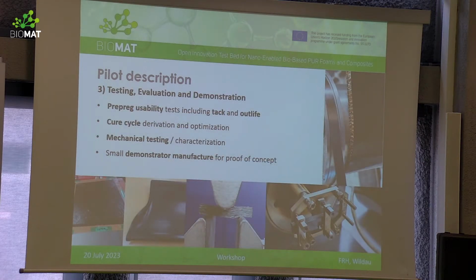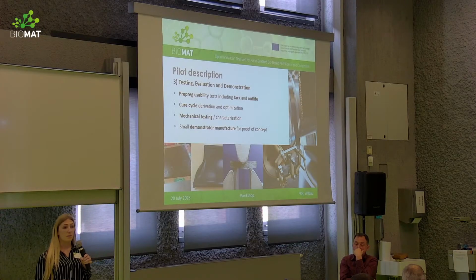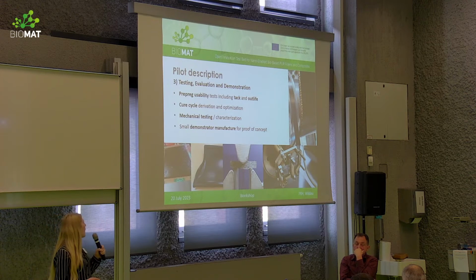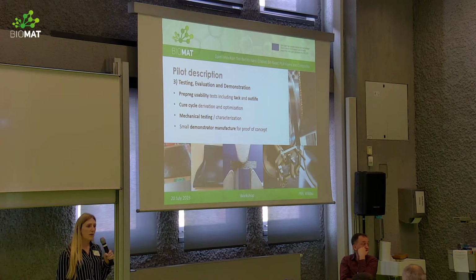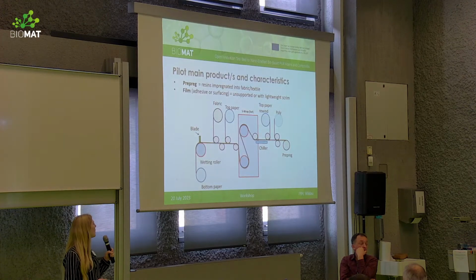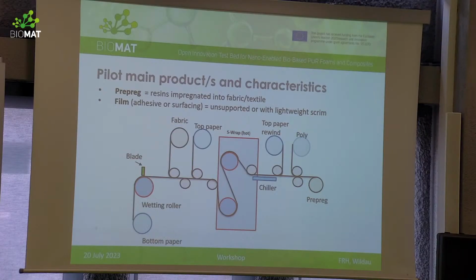And then once we've made the prepreg, we can perform prepreg usability tests like tack and outlife. We can optimize the cure cycle, and we can also produce panels and perform extensive mechanical testing. We can also make small demonstrator parts as well. So on our pilot line, we can make two main products: prepreg, which is where you impregnate resin into a fabric, or we can simply make a resin film. Resin films are typically used for adhesive or surfacing applications.